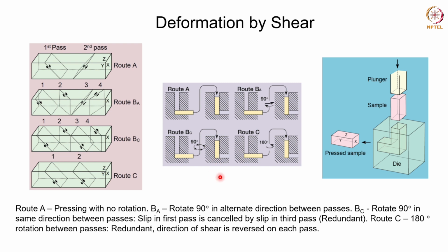Now what is done between two consecutive passes would give rise to a particular type of ECAP process, and these different routes of ECAP are given names like this. For example, route A, that is pressing with no rotation between passes, as you can see in the first picture of this diagram. In the first pass you deform the material, take it out, and then again insert it inside the die without rotating it. Now if you rotate it, then you have the other ECAP routes. For example, in case of route BA, the workpiece is rotated 90 degrees in alternate direction between passes.